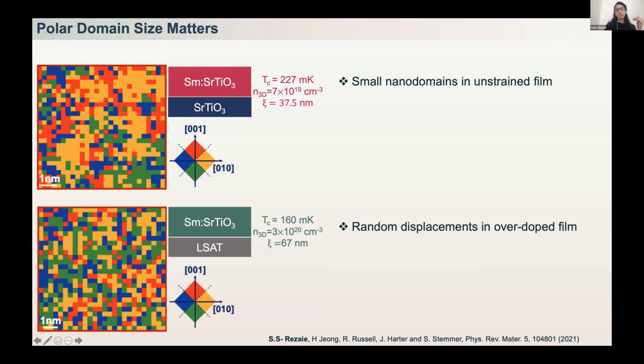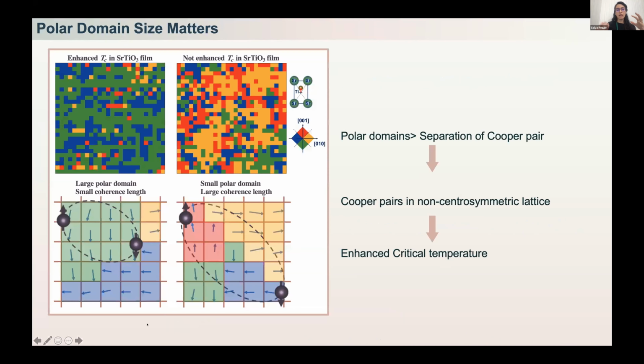You can see that for the case of unstrained film, we still have these domains forming, but compared to the strained films, they are happening on a smaller length scale. And here, for the case of doped strontium titanate on strained films, we mostly have random displacement. So that brings us to the conclusion that if we have polar domains that are larger than the separation of the Cooper pairs, that will lead to the enhancement in superconductivity, because the Cooper pairs sitting in the structure are seeing only the non-centrosymmetric lattice.